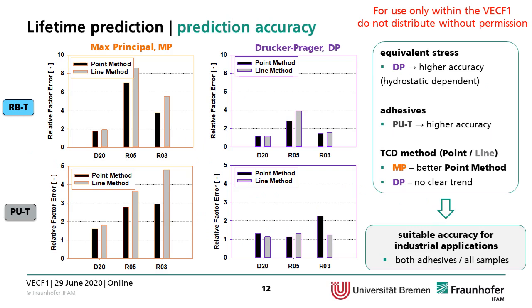Here you can see the prediction accuracy using the max principal stress as equivalent stress and the Drucker Prager as equivalent stress for both RBT adhesive and PUT adhesive. By looking at the equivalent stress, the Drucker Prager equivalent stress has a higher accuracy. As you can see here, the relative error factor of the purple curves is much smaller than the orange curves. Regarding the adhesives, we had a higher accuracy with the PUT adhesive, and regarding the TCD method, point method or line method, for the max principal stress, it was better with the point method, and for the Drucker Prager stress, there is no clear trend.